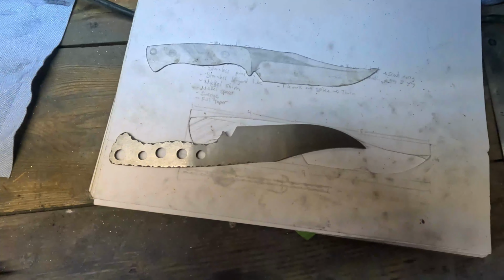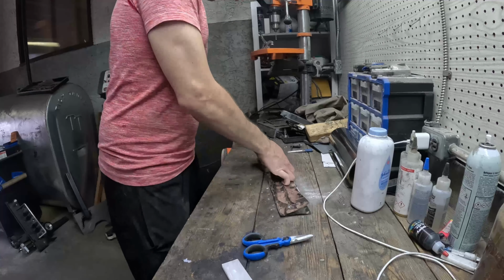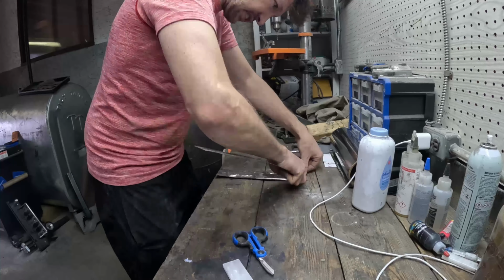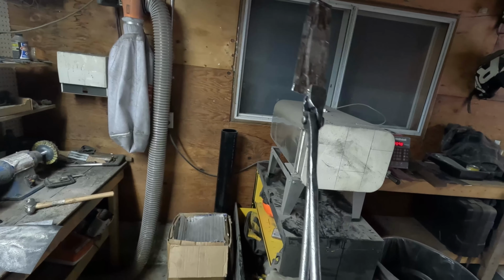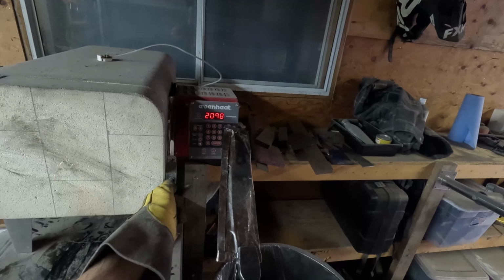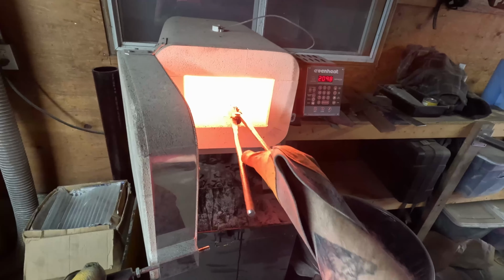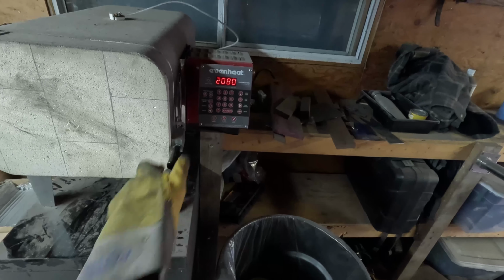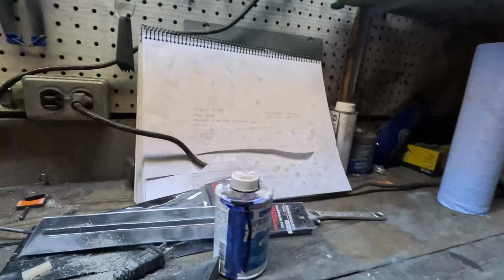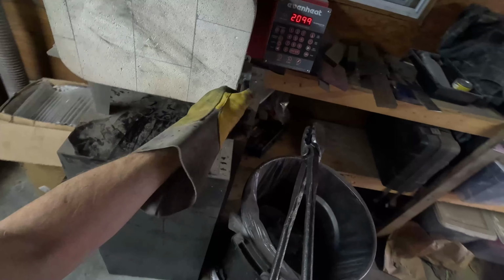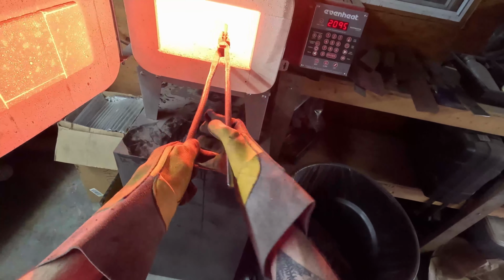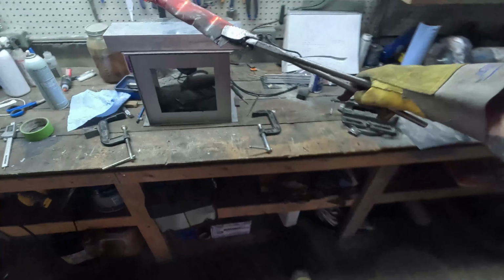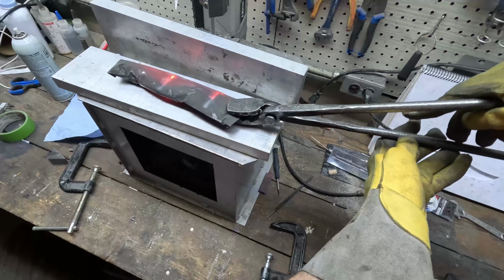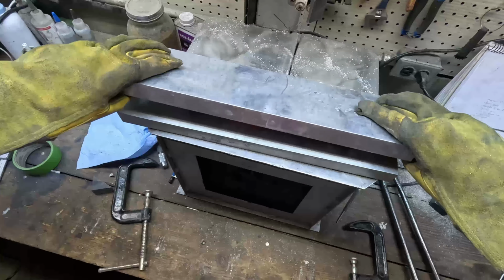Here I'm making an airtight pocket with this specialized aluminum foil so that there is no oxygen in the heat treatment process of the stainless steel. If there was oxygen in the process, it would decarburize the carbon in the steel and make the steel not as good. So to achieve this, I use this specialized aluminum foil and make a small pocket. Then I put a thin coating of baby powder so it doesn't stick, and it burns the baby powder with the oxygen instead of reacting with the carbon first. And then I press on everywhere around the blade so it removes the oxygen and makes it super tight.